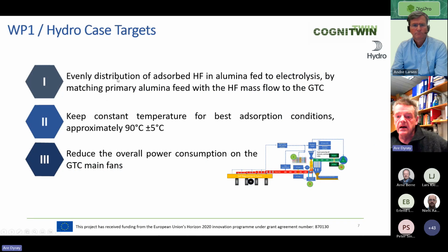We had targets for each of them, and that was evenly distributed HF absorbed in the alumina fed to the electrolysis. Keep the temperature within 90 plus minus 5 degrees, and reduce the overall power consumption of the GTC main fans in the system.